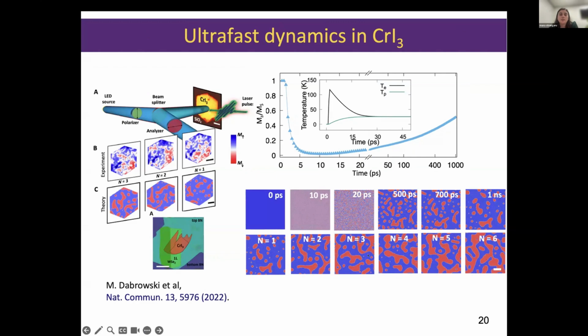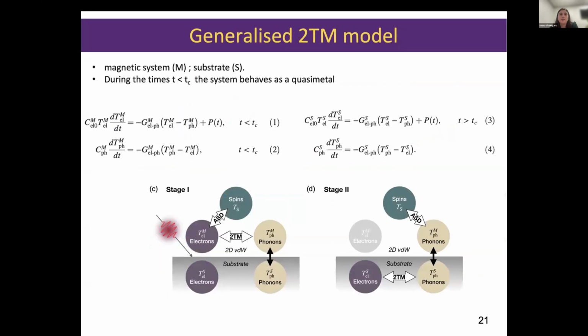So we were able to see a rich domain formation when we excited our magnetic system more strongly. But by exciting so strongly, the type 2 form of the magnetization curve was lost. So we are now back to a type 1 where we see this recovering. We observe the creation of domains, but we would like our model to also predict this type 2 demagnetization. So we went back to the 2-temperature model and created a generalized form of this 2-temperature model, of this coupled equation between the electronic and phononic temperature.